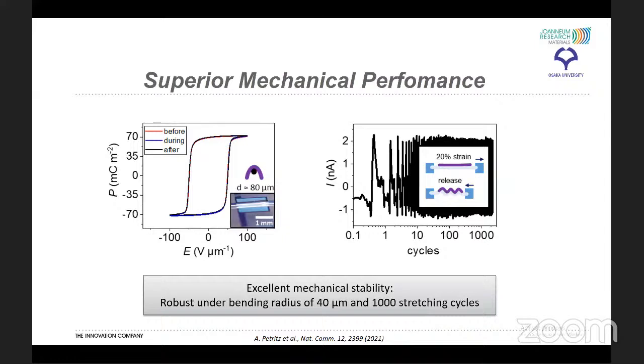The mechanical robustness of the ultraflexible sensors is also exceptional. The polarization hysteresis remains completely unchanged during bending around an 80 micrometer thin wire, as shown here on the left, and the sensor signal is also stable over more than 1,000 stretching cycles as plotted on the right.